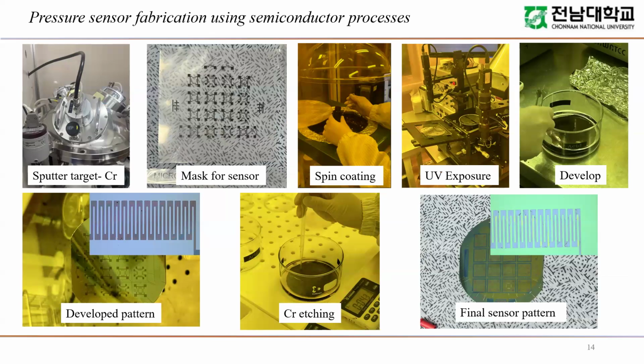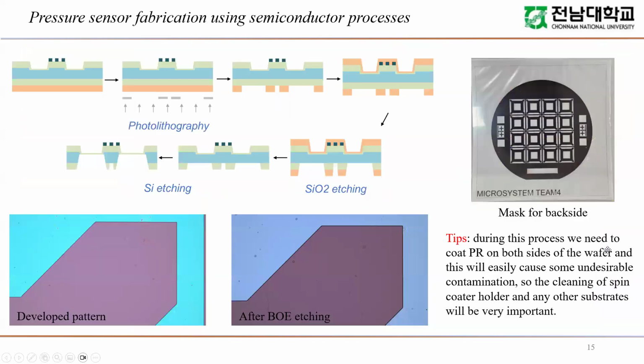This is the detailed process. First, we deposit the chromium here, and after deposition, using this film mask, we conduct the photolithography, following from spin coating and UV exposure to developing the pattern. Then we do the chromium etching process to make the sensor pattern. And after removing the PR, we get the final sensor pattern as shown in this figure.